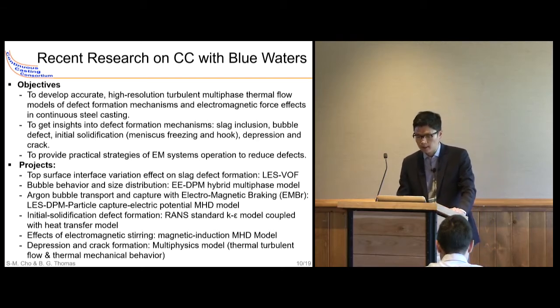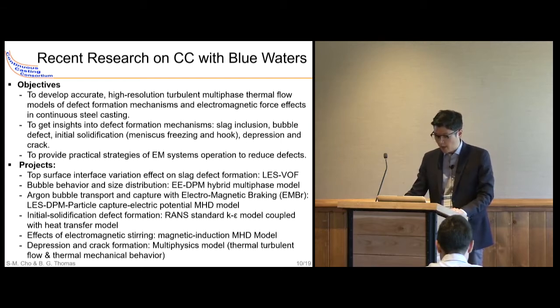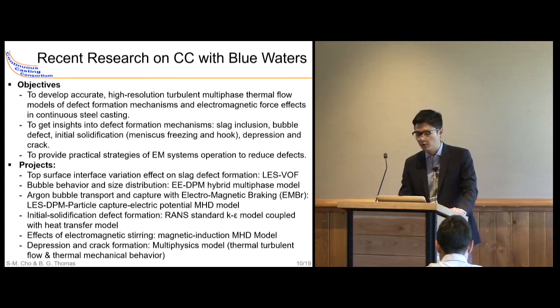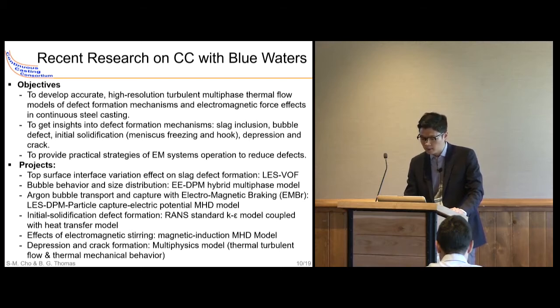Top surface interface variation effect on the slag entrainment defect using LES coupled with VOF, and bubble behavior and size distribution using the new hybrid multiphase model, EE-DPM, and argon bubble transport and capture with the electromagnetic braking effect using LES coupled with the DPM particle capture model and the electric potential MHD model, and initial solidification defect formation modeling using the RANS standard k-epsilon model coupled with the heat transfer model.